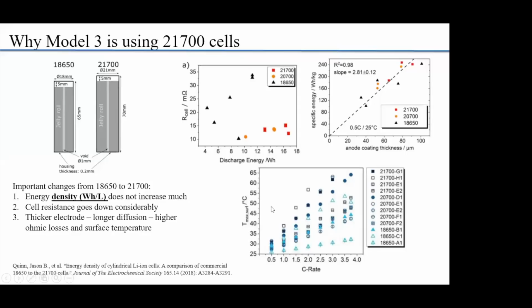Basically, 21700s have a much higher discharge capacity and they can store more. In fact, it's about 3.5 amp hour for 18650, whereas this one, 21700, goes up to 4.8 to 5 amp hours. So you have higher energy storage going from 18650 to 21700, but the density doesn't increase much. That is what that graph shows.